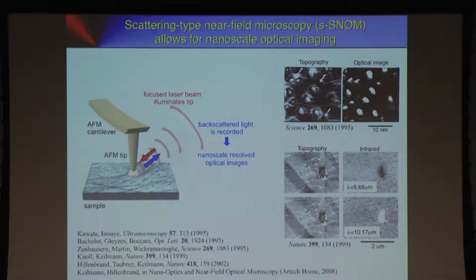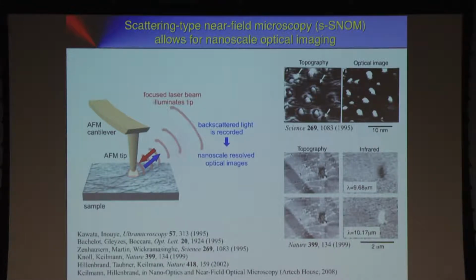And so the basic idea is the following. We take a standard atomic force microscope tip, then we shine light on the tip, and we collect the backscattered light. By doing so, in this early work published in Science, they claimed 7 angstrom optical resolution. And Fritz Keilmann, then my supervisor, brought this technique to the infrared in '99, showing here spectroscopic contrast of 2 polymers. So just light scattering at an AFM tip, and that gives the resolution.